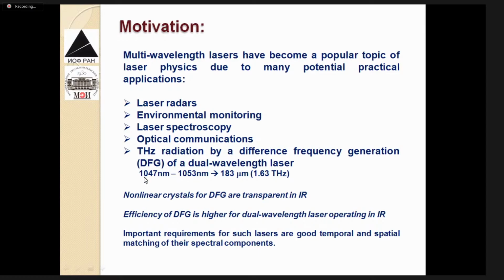Especially when we talk about difference frequency radiation, it is necessary to mention that many nonlinear crystals that are effective for this purpose are transparent only in the infrared, but not in visible radiation. Also, regarding the energy efficiency of the DFG, for infrared radiation the efficiency will be high because you use only the difference of two photons, and if these two photons are in the infrared, their energy is less, and that's why the efficiency is high.